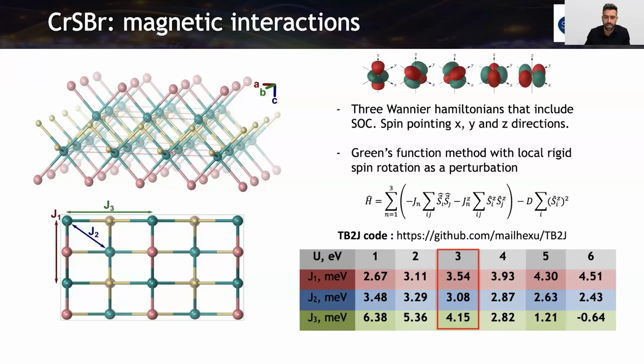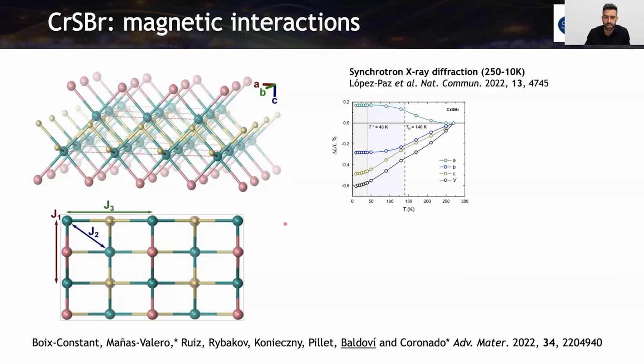So in this case, we compute using 3 Wannier Hamiltonians. We add the spin orbit coupling, and the spins are pointing along X, Y, and Z directions. And with the Green function method in the TB2J code, as you can see here, we compute the magnetic exchange interactions for different Hubbard-U. One interesting thing in this material is that when we were studying the magnetism, this work appeared that was published afterwards by Lopez Paz in Nature Communications. At that time it was an arXiv preprint, and they were measuring the evolution of the crystal structure with temperature.